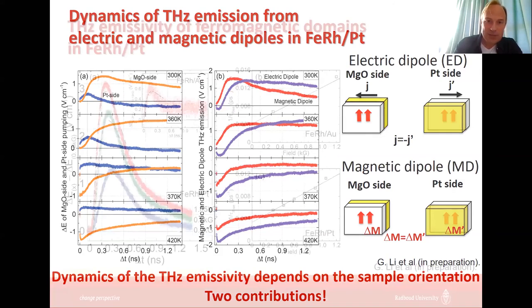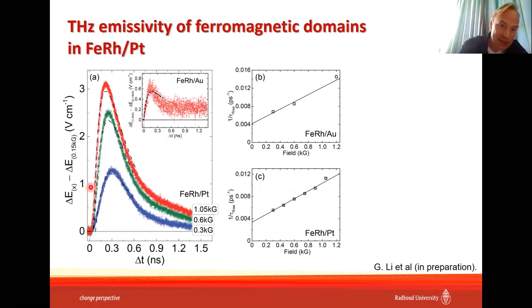We performed measurements as a function of magnetic field, and what we plot here is the difference: the measurement in a certain magnetic field, let's call it X, minus the measurement in a very small magnetic field, 0.1 kilogauss, which will not affect spin dynamics on this time scale. So basically what we do is exclude those nuclei that had enough time to be oriented in this very small magnetic field, and these are nuclei which were existing in the medium already before pump one. And you can see here very slow dynamics,